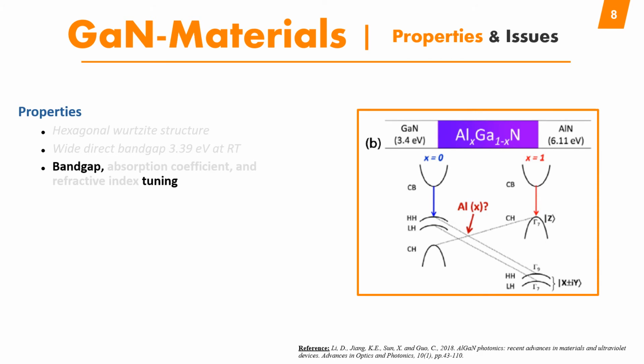We mean that, for example, if we take aluminum gallium nitride as an example, and x is the aluminum concentration in the material, if we change x, consequently the gallium will change. So aluminum will change and gallium will change. We can say that aluminum gallium nitride, a ternary alloy, is between the gallium nitride band gap and the aluminum nitride band gap. If the concentration of aluminum is 1, we are talking about aluminum nitride, and if the concentration of aluminum is 0, we are talking about gallium nitride. So we can tune the band gap of aluminum gallium nitride from 3.4 electron volts for gallium nitride to 6.11 electron volts for aluminum nitride. As we can see here, we can tune whatever energy band gap we need.